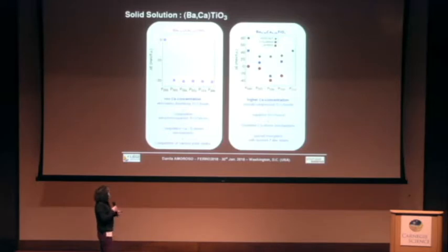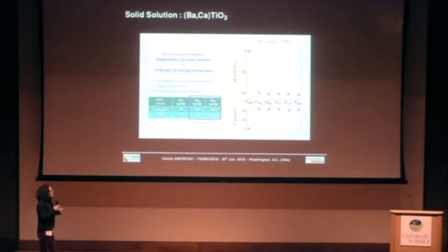But now let's focus on what happened in this low calcium concentration case. Well, in fact, this energetics is an anisotropic energy landscape because we have the appearance of different monoclinic phases, and the value of the polarization for all of these states is exactly the same. And to this corresponds a huge enhancement of the piezoelectric response, because the system now has the possibility to experience a different orientation of the polarization without any energy cost.